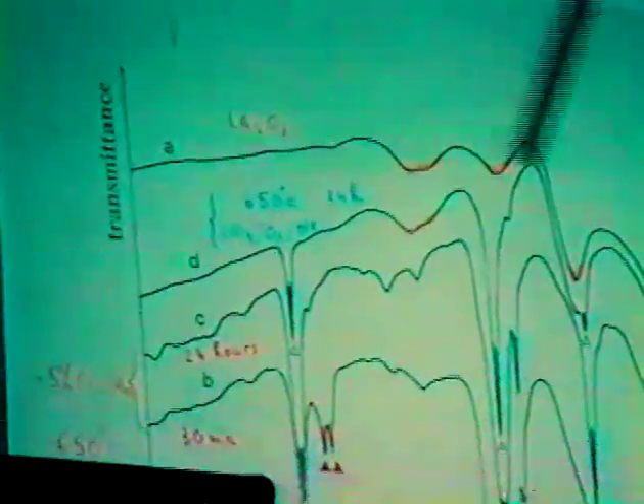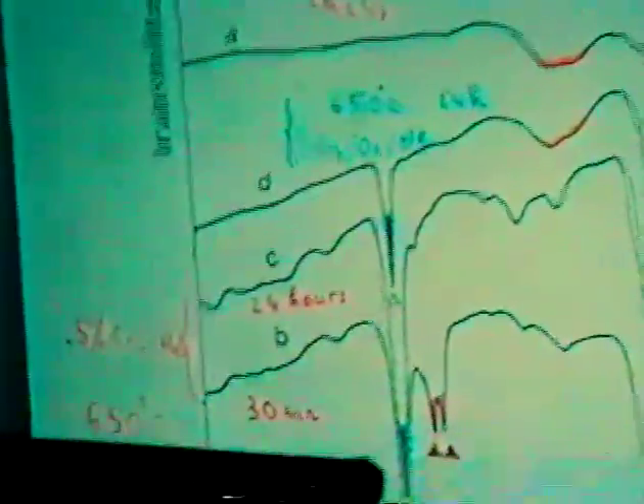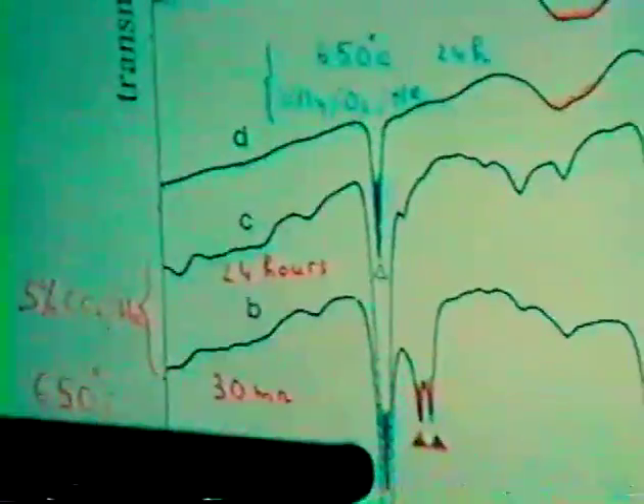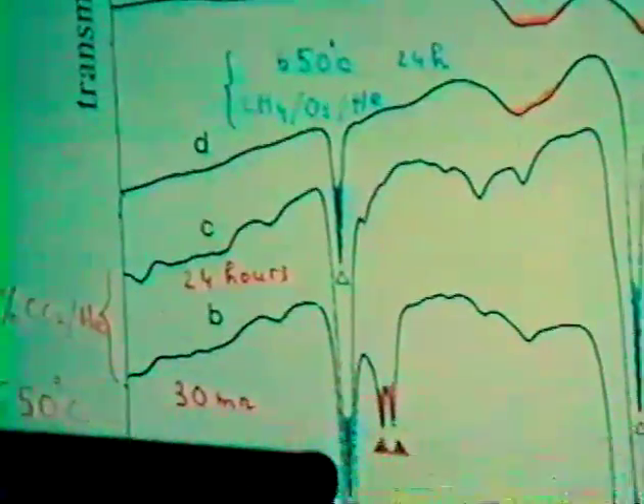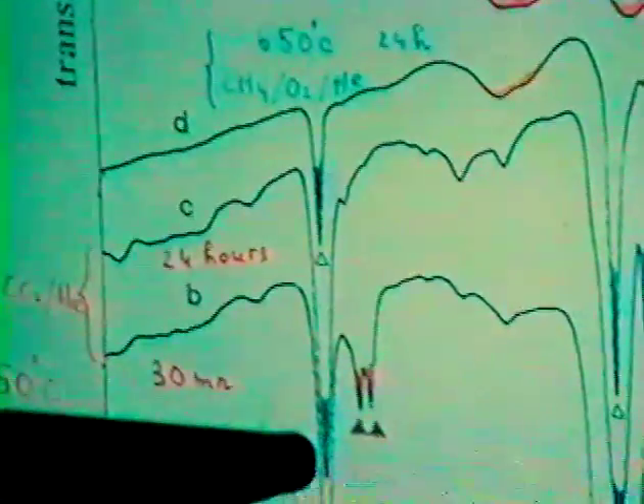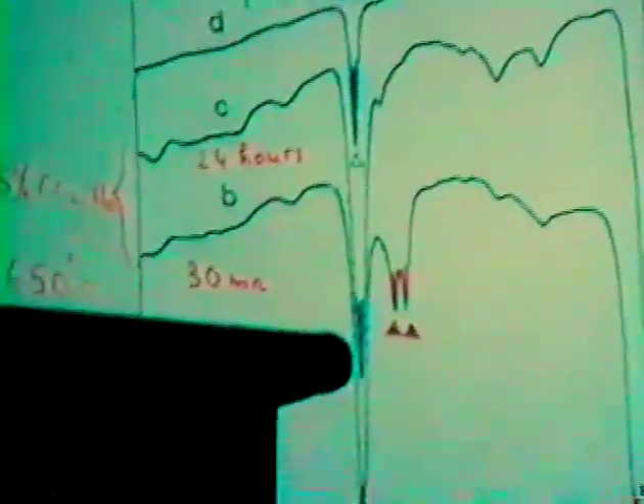So in this transparency, I have summarized the main results of the study. Here is the parent oxide with, in orange, the lattice modes and the combination lattice modes, and we have treated the catalyst either with a 5% mixture of CO2 and helium at 650 degrees C, or with the oxidative coupling reaction.